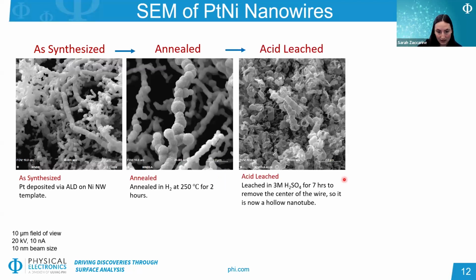And then these were acid leached. So again, the goal of this was to pull out a bunch of that bulk nickel core before these are incorporated into a cell, because otherwise that will happen during fuel cell operation, which can lead to degradation of the cell over time. And we see that in fact they are quite hollow. They're very thin looking. We also notice that some of them have broken up. Generally, they look like there are shorter pieces compared to the synthesized and annealed samples. However, we see that they're also intact, so they're not completely falling apart after this acid treatment.